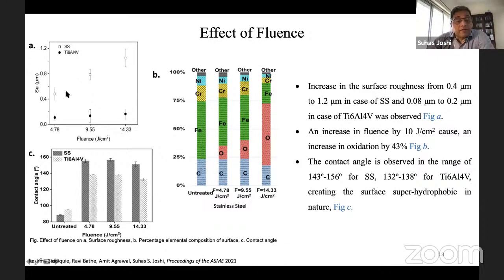If you see the surface roughness, you will find that a greater surface roughness is produced on the stainless steel samples compared to the titanium because of their inherent strengths. However, because of the greater roughness, these surfaces have close to super hydrophobic characteristics, with the contact angle varying between 143 and 156 degrees on this stainless steel, because the roughness is quite large and sort of non-uniform or randomly distributed. At the same time, the oxidation levels on the surfaces are very high, so there is a possibility of corrosion. So you need to protect the surfaces.